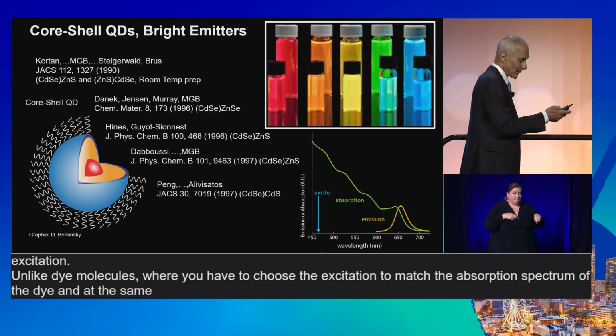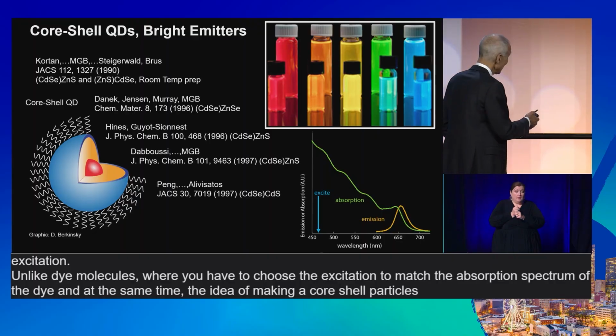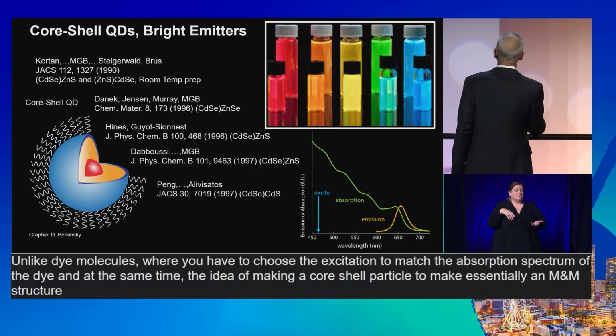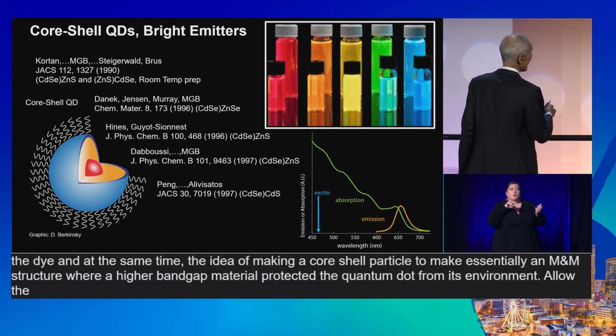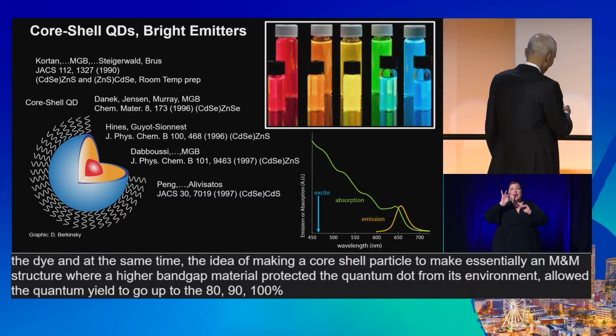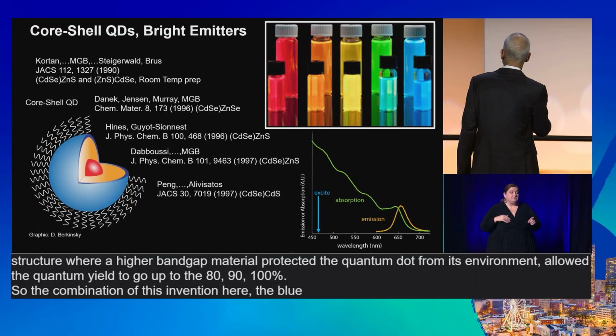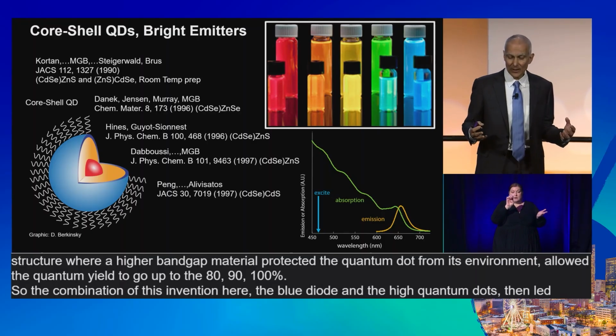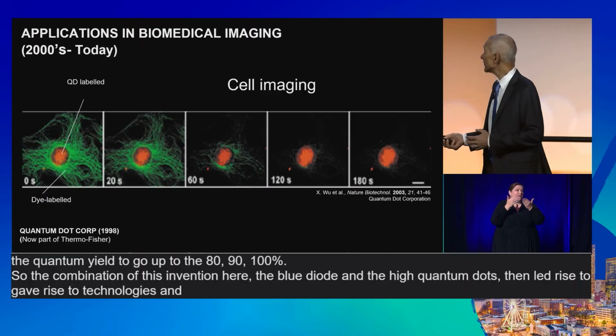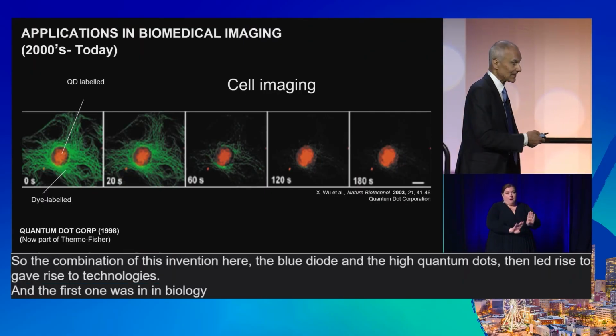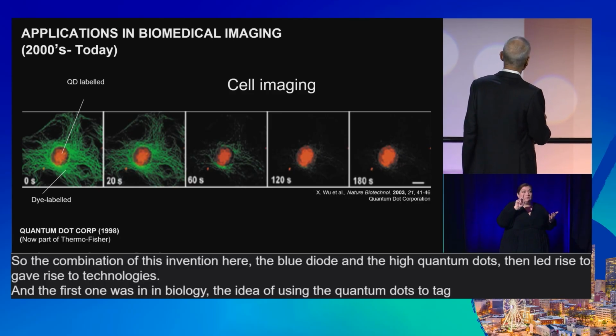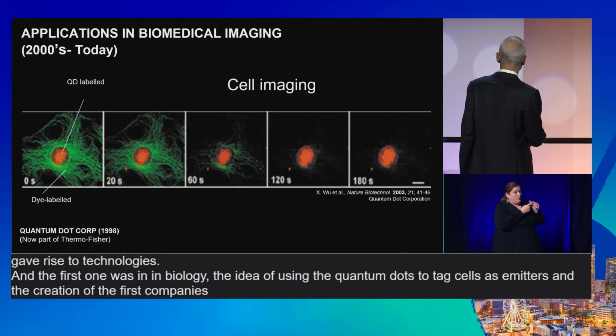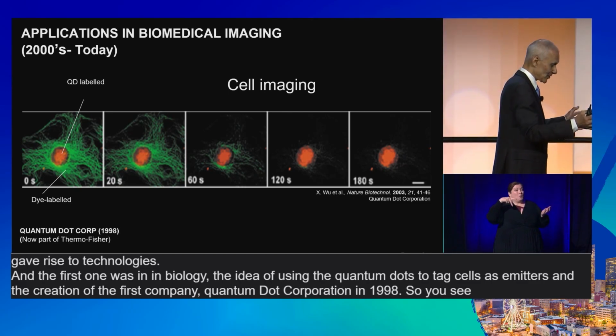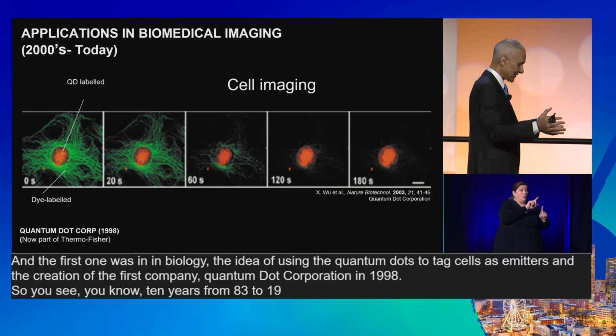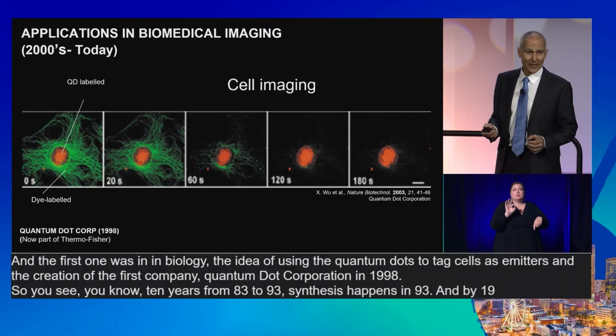And at the same time, the idea of making a core shell particle, essentially an M&M structure, where a higher bandgap material protected the quantum dot from its environment, allowed the quantum yield to go up to 80, 90, 100%. So the combination of this invention, the blue diode, and the high quantum yield dots then gave rise to technologies. And the first one was in biology. The idea of using the quantum dots to tag cells as emitters, and the creation of the first company, Quantum Dot Corporation, in 1998. So you see, 10 years from 83 to 93, synthesis happens in 93, and by 98 now we're talking about commercialization.